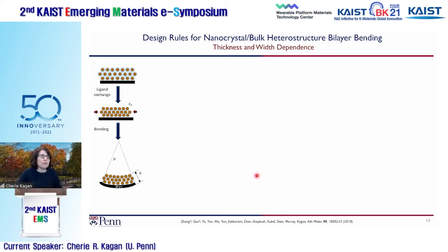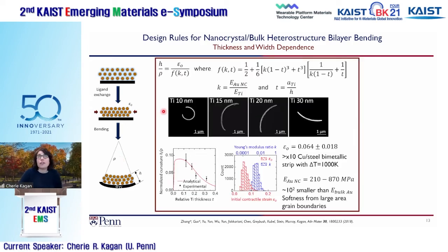And so I'll only briefly go into this in the interest of time, but what we did is that we controlled, for example, the thickness of the titanium layer in comparison to the thickness of the nanocrystal layer, and we would measure how much it bent by looking at the curvature of the materials in the electron microscope. And so this equation looks crazy, I understand that, but actually this is an equation that describes the thickness of the bilayer structure in comparison to the radius of curvature.